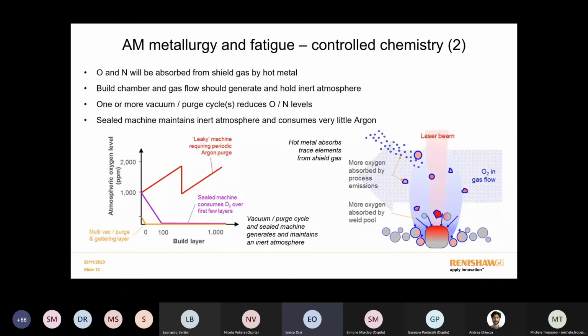So if we look at the way that oxygen and nitrogen can get into the alloy, there are basically two ways: if the atoms of oxygen and nitrogen are already included in the alloy itself, or if they're taken into the alloy by the process. We want to achieve alloys with very low content of oxygen and nitrogen to achieve the best possible elongation and resistance to fatigue. However, the environment around us is not helping us, so we want to control the inert atmosphere of the machine to a very tight specification. In here, you can see what happens.